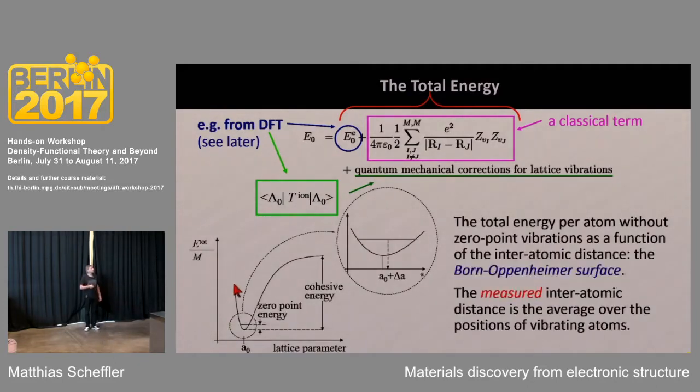If you look at a typical curve, which we also will calculate in the next days, a typical curve going actually from interatomic distances which are large, and you're going to smaller and smaller ones, you're going to a minimum, and then behind the minimum, getting even closer, there's a very steep rise. This steep rising comes from a Pauli repulsion because electrons don't want to be compressed in their space, and this really is a smooth and somewhat softer function as on the left side.